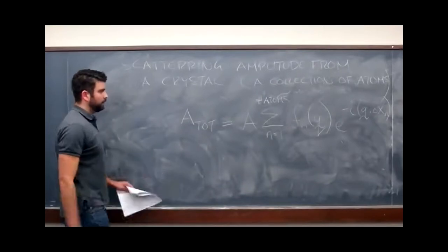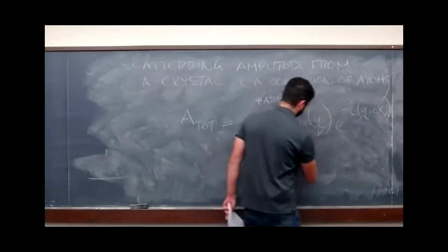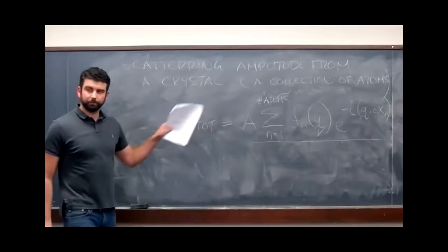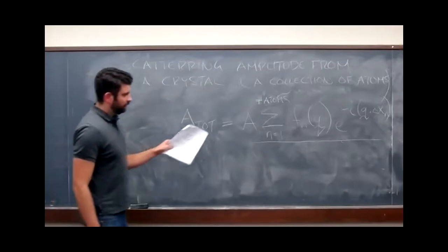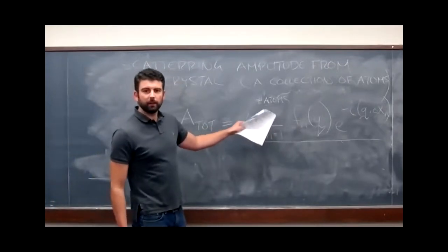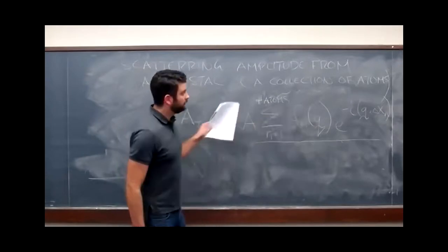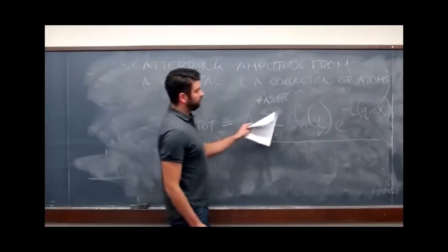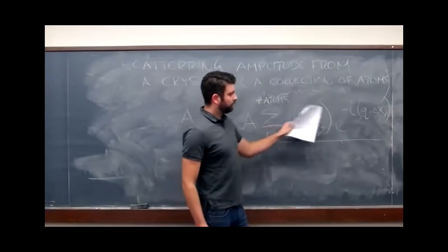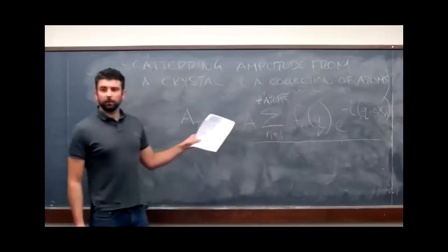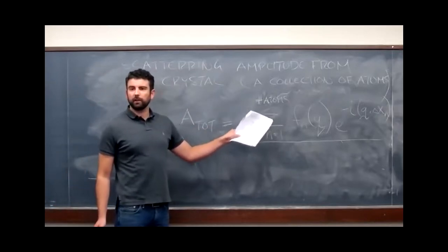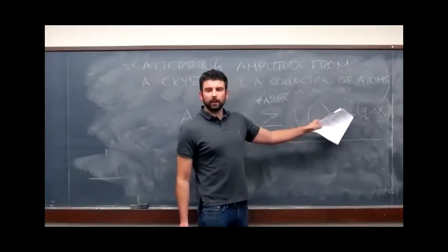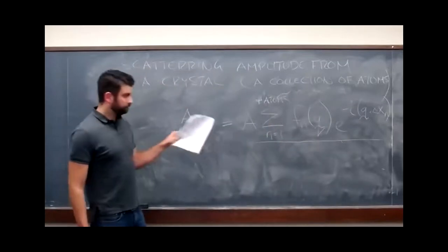So let's take a pause right here, looking at this equation. We're going to be talking about this equation for a good part of the rest of the day. But what's important to remember is this is it. We're done here. If you want to calculate the scattering power from a collection of atoms, this is all you need. You can calculate it here. While this was a problem when they were first developing these things, or trying to figure out the diffraction condition, these days we have computer programs where things like molecular dynamics will tell you the position of every single atom in an amorphous volume, in a crystal. If you know this, you can directly calculate the scattering amplitude. So you don't have to make any assumptions here.